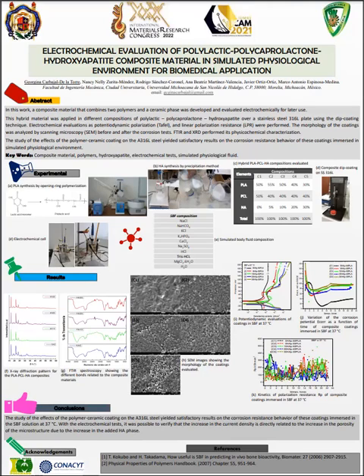Figure I. In these results, the increase in the hydroxyapatite phase promotes a direct increase in the anodic current. With these results, we can conclude that the study of the effects of the polymer-ceramic coating on the stainless steel 316L yielded satisfactory results on the corrosion resistance behavior of these coatings immersed in the simulated physiological environment.